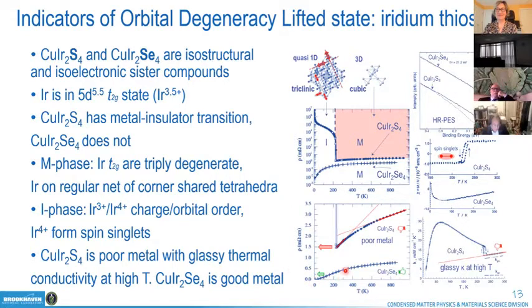One is actually a very good metal, selenium variant. The other is not. The other is actually having resistivity that is not really metallic. It's actually orders of magnitude or order of magnitude larger than it should be to be considered a proper metal. And it has various other anomalies at high temperature, such as weak Fermi edges and glassy thermal conductivity. So one of the questions that we wanted to answer is why this high temperature regime has such poor metallicity in the sulfur case.